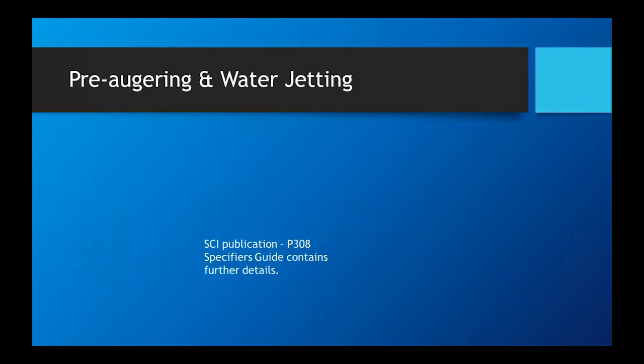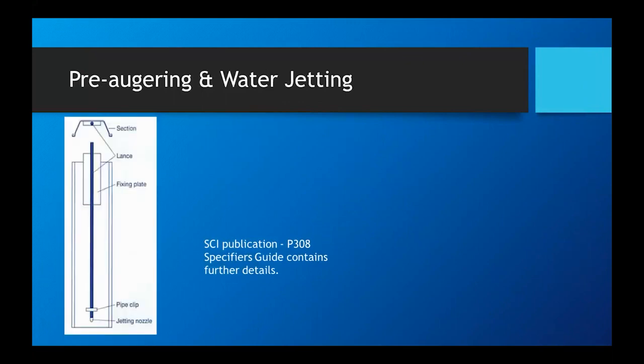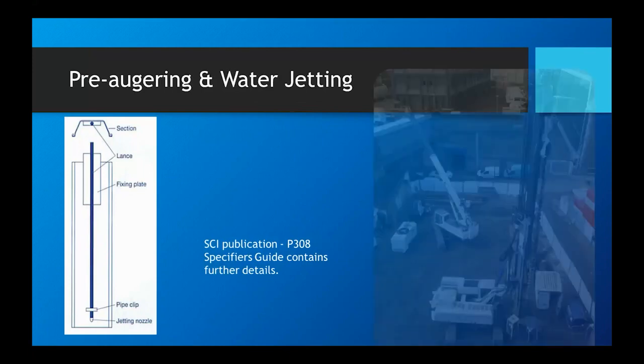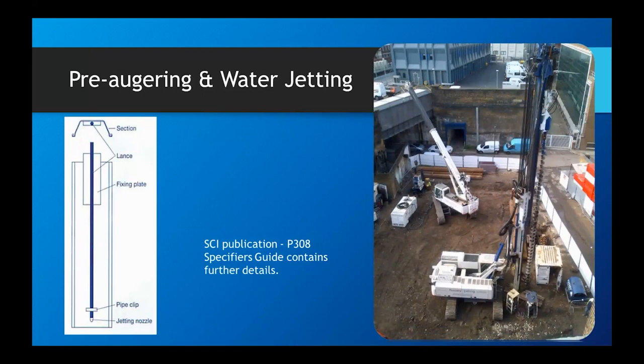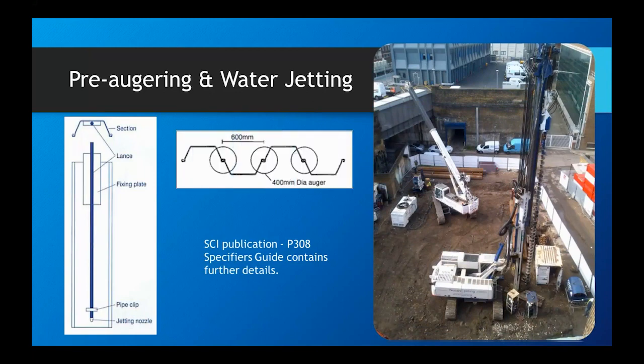In tougher driving conditions, so dense ground or stiff clays, one can use a combination of pre-augering and/or water jetting to assist in getting the piles in. As I mentioned, the SCI publication 308 gives a lot more detail on it, but you can see on this particular site, this is a job in Southwark where you've got dense gravels overlying London clay, and on this project we pre-augured with a 400 diameter auger at 600 centres all the way around there to facilitate driving the piles. Other people may well water jet to achieve the same.